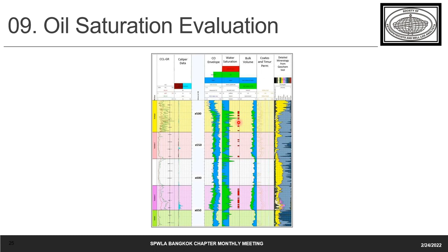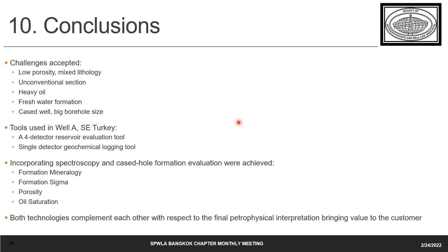Regarding the porosity, we had available the neutron and density porosities from the open hole data, but we also computed them independently from the inelastic curves of the four detector pulse neutron tool. From the single detector, which is the geochemical tool, the matrix density was determined based on the resulting mineralogy and computed from mineral volumes. The final porosity was thus derived and improved using the bulk density from the open hole data and the matrix density from the pulse neutron geochemical tool.